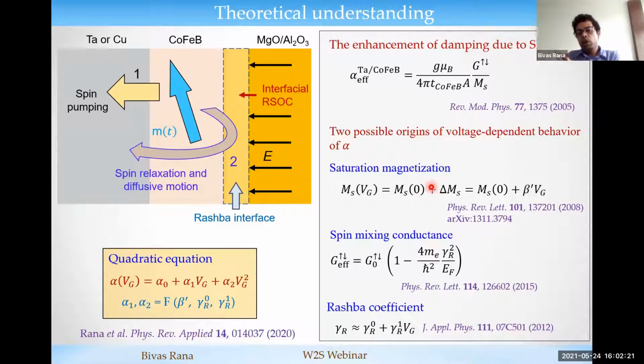But there may be two possible origins of the voltage dependent behavior of alpha. First of all, the saturation magnetization, which we modulate by gate voltage, and here is the saturation magnetization. So that can give a voltage dependent behavior of the damping. And second is the spin mixing conductance of the system, which may depend upon the gate voltage, because some part of the spin current is also pumped into this layer, where we know the existence of Rashba spin orbit coupling. So some spin currents are relaxed there, and after the spin accumulation, some of them are relaxed back, through diffusive motion, into this heavy metal.